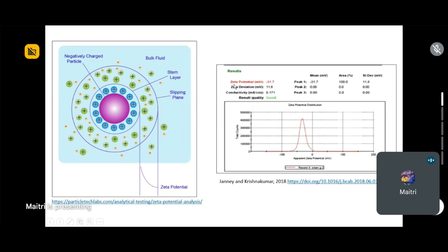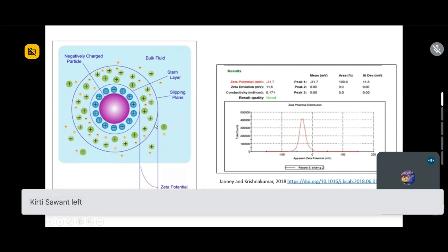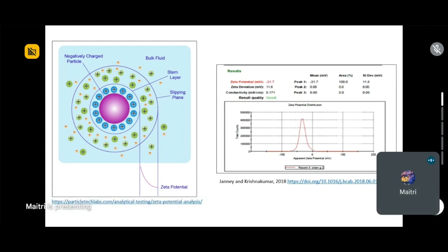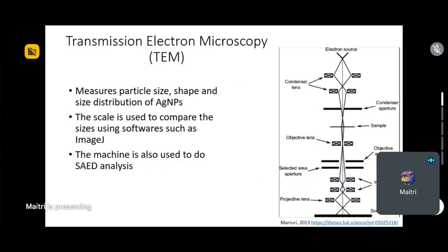Now, what is this graph telling? That this zeta potential over here in the red color is minus 31.7 millivolts. So, what does this mean? The result quality is good. It means that the zeta potential between this and this is minus 31, so the amount of repulsion between these two will be minus 31 millivolts. So the higher the value of the zeta potential, the higher will be the repulsion between these ions and molecules. And because they repel each other, they will not combine with each other and will not tend to aggregate. So a higher zeta potential value indirectly means a higher potential stability of the AgNP and lesser chances of aggregation of the AgNPs. I hope this was clear.